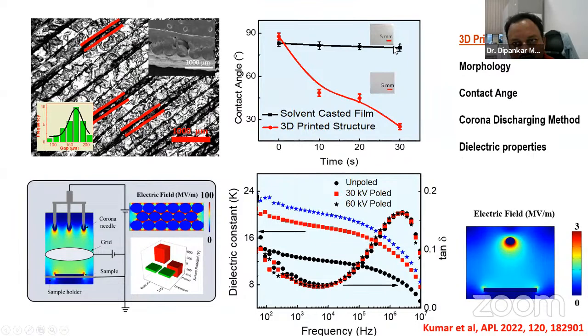For example, this is the normal sample, but if we do the 3D structure, then contact angle is getting reduced. Similarly, dielectric property, unpoled system, this is the normal one, but then if you pole them, apply the high electric field, the dielectric constant is also changed.